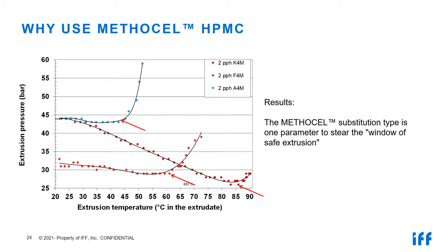Here we are comparing 3 very different behaving cellulose ethers. Let's start with the dark red curve, which shows first a long, very linear drop in pressure, because I said already, if you heat up a polymer solution, the viscosity must drop. But at the end of the scale, somewhere at 80 or 85 centigrade, the extrusion pressure drop stops and there is a rise in pressure. And this is due to the flocculation of the cellulose ether. But this METHOCEL K chemistry is very well known to lead to very, very high gelation temperatures. So the safe window of operation here is somewhere up to 70 degrees, which is probably good enough for nearly all cases.